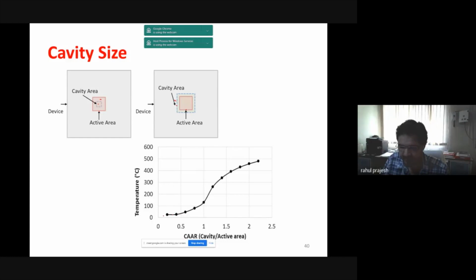We have simulated different cavity to active area ratios and found that approximately 1.5 to 2 is a good ratio where you can get a very good temperature for a given power. That means your cavity area should be at least 1.5 times larger than the active area. And if you go beyond 2, the mechanical issues will take place and your membrane will be very fragile and it can break. So there is a trade-off between the mechanical stability and the power consumption. So 1.5 to 2 is a very good range for the cavity to active area ratio.